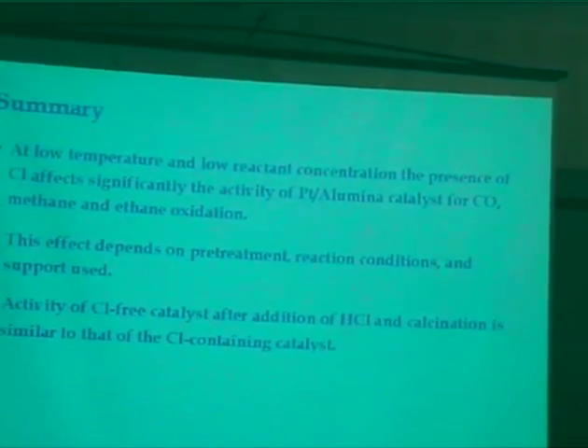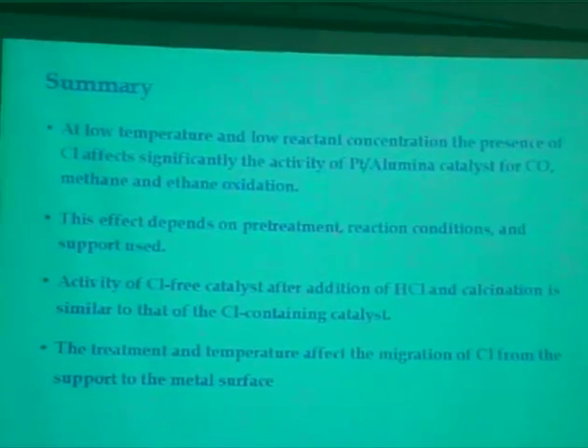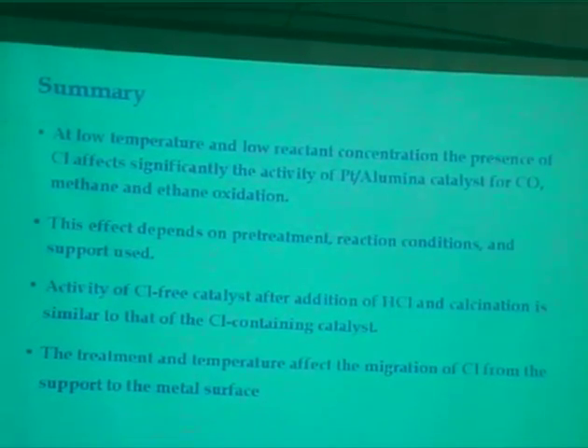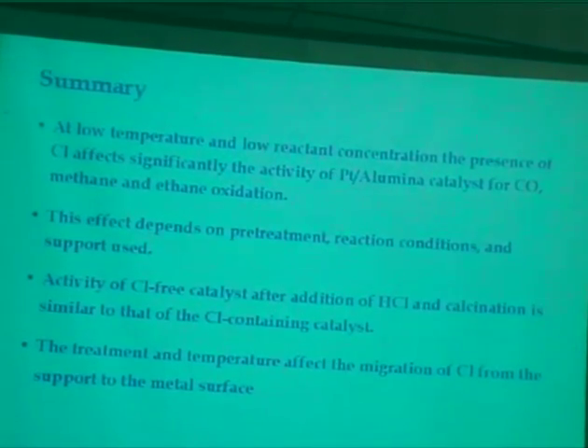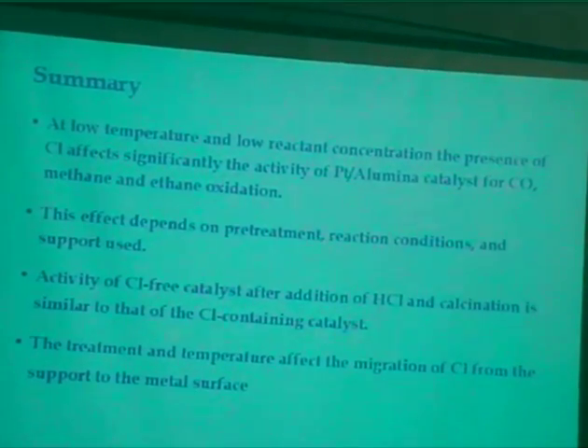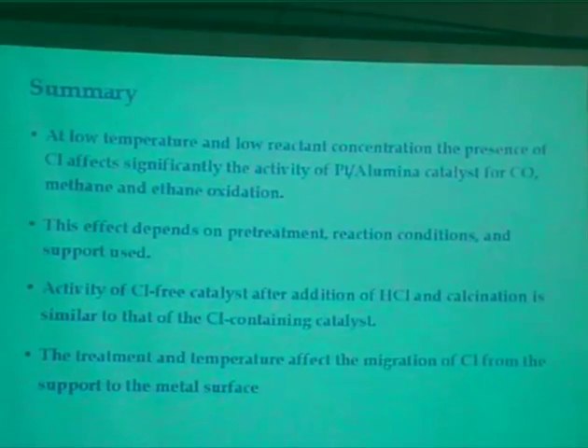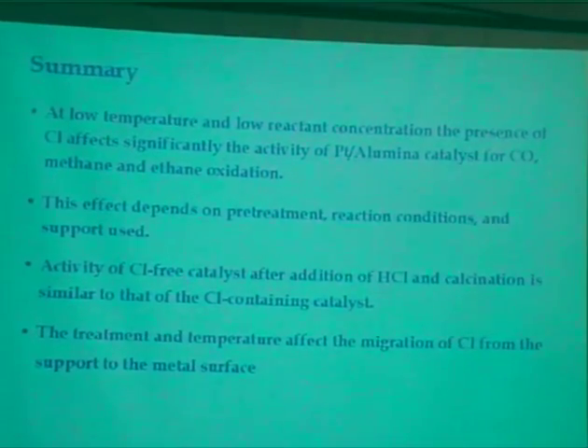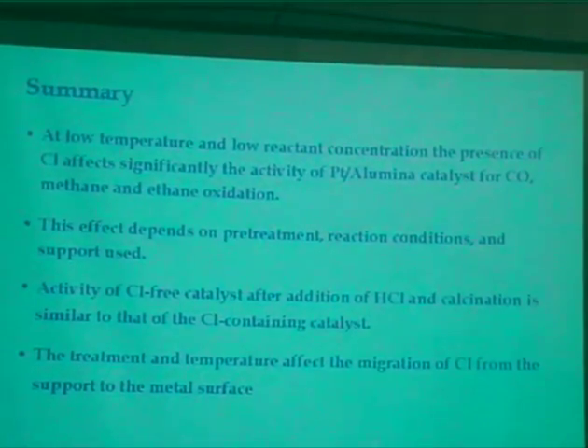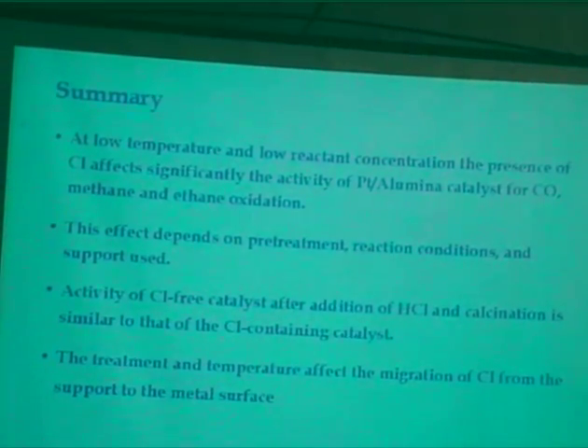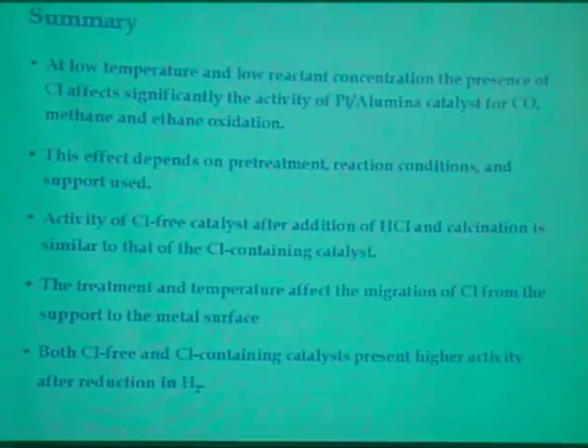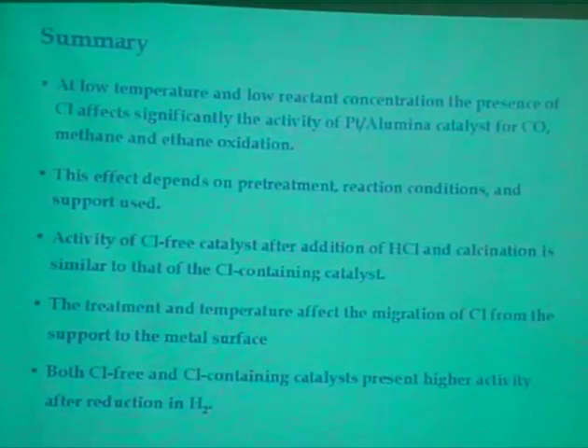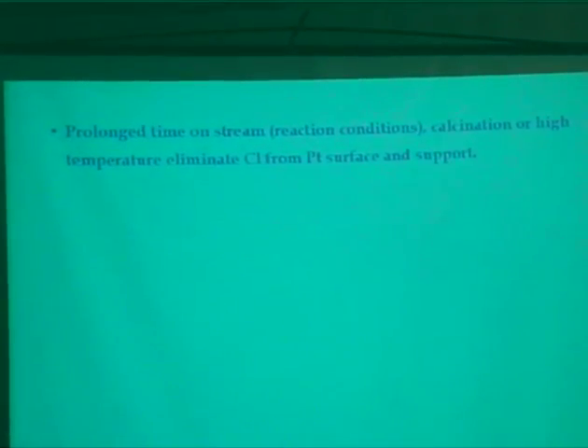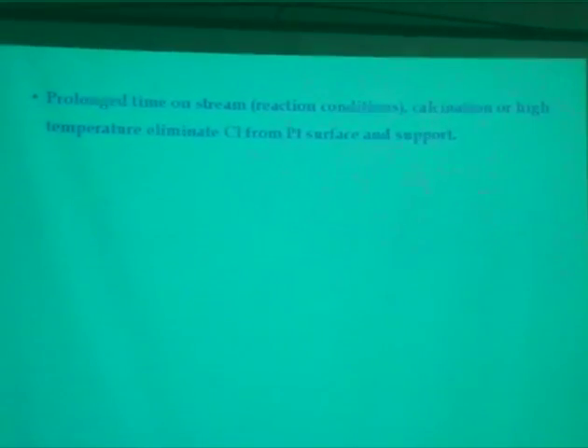So you can be doing this intentionally, and I'm sure this is done in industry actually, for certain reactions where you need to have the chlorine there, and part of the chlorine will end up in your metal and improve your selectivity most likely, or in your support and improve the acidity of the support. And there is a migration of chlorine from the support to the metal surface. I don't know how fast this occurs. Reduction, of course, gives you the metallic surface, which is the most active for oxidation reactions. But if you do these things for a long time, you're able to eliminate the chlorine from the surface.